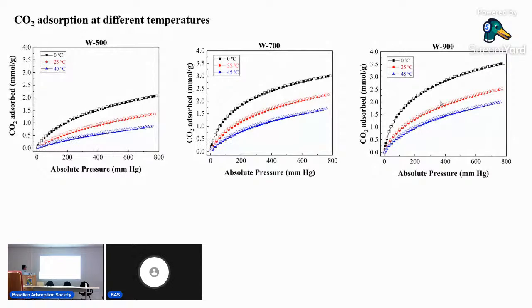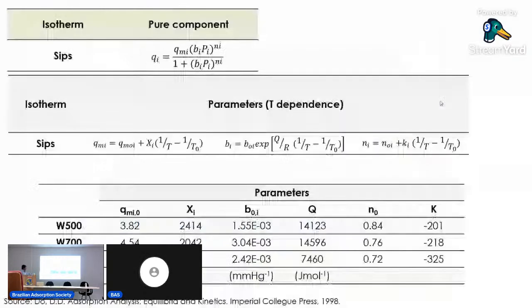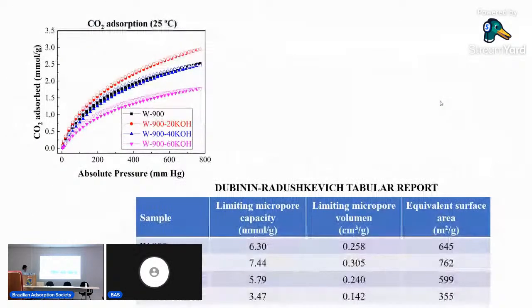It's possible to compare the results, and here now we can compare the absorption capacity of the material after chemical activation, which is a basic substance. Also, we observe an increase with 20% of addition of potassium hydroxide in comparison with the sample with only thermal treatment. And here, this is the best result with the addition of this basic component.